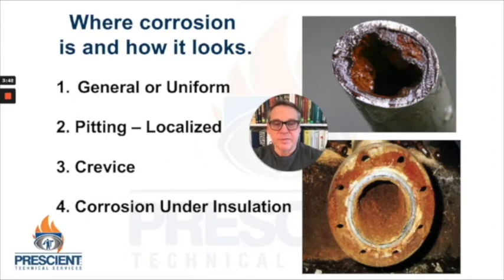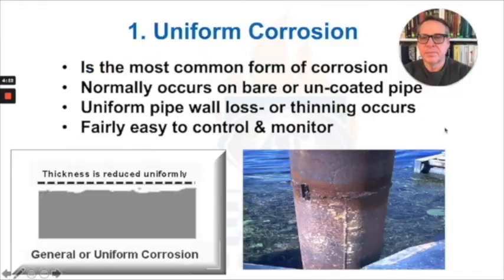Here are just four of the many ways that you could describe corrosion: general or uniform corrosion, pitting or localized corrosion, crevice corrosion, and corrosion under insulation. I'm going to provide what I believe are some interesting technical papers about how some of these have caused major problems in refinery explosions and other types of major industries. Uniform corrosion is the most common form of corrosion. It normally occurs on bare or uncoated pipe, and you can see here in the picture underneath mine that this pipe, sitting mostly submerged for long periods of time, has lost a somewhat uniform amount of wall thickness.